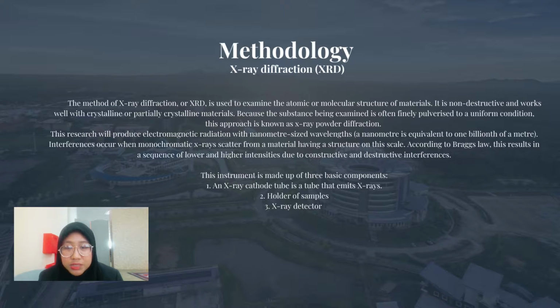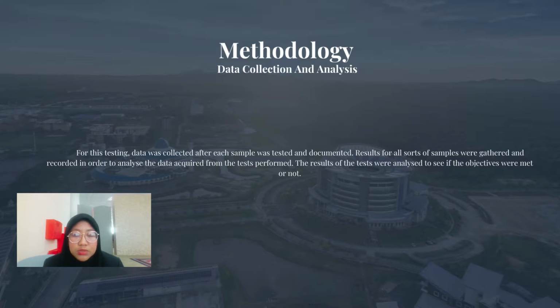Okay, the method of X-ray diffraction, or we call XRD, is used to examine the atomic or molecular structure of a material. It is non-destructive and works well with crystalline or partially crystalline material because the substance being examined is often finely pulverized to a uniform condition. This approach is known as X-ray powder diffraction. For this testing, data was collected after each sample was tested and documented. Results for all sorts of samples were gathered and recorded in order to analyze the data acquired from the tests performed. The results of the tests were analyzed to see if the objectives were met or not.